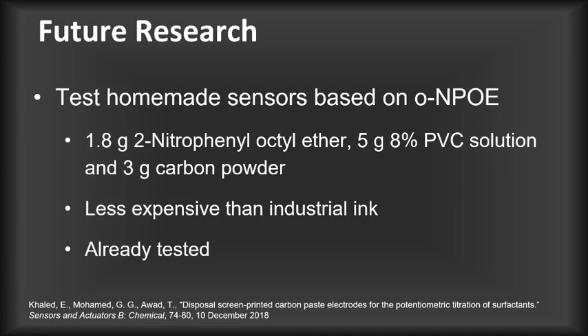Then, I wanted to test the homemade sensors based on the ONPOE, which I first mispronounced as "oh nope," with the 1.8 grams of 2-nitrophenyl octyl ether, 5 grams of 8% PVC solution, and 3 grams of carbon powder. Apparently this is less expensive than the industrially prepared inks. The good thing about this is that it has already been tested and it works very well. We just haven't tested it on paper yet. So that's one of the things that I want to leave open.